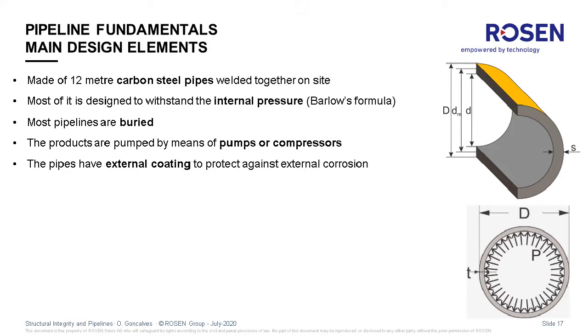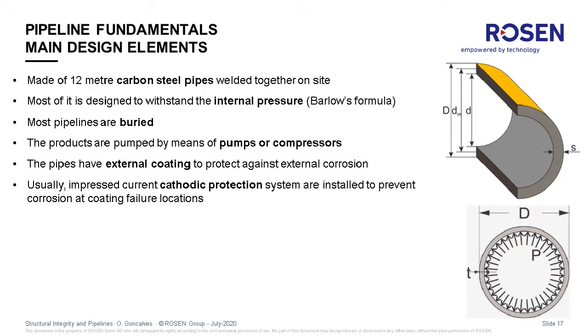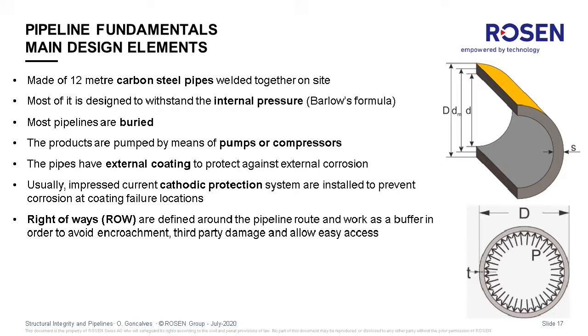Most of the pipelines have an external coating, the objective of which is to protect against external corrosion, which is caused by the soil surrounding the pipeline. And as a second barrier for corrosion, there is cathodic protection, because after some time it is expected that the coating might have some flaws, and in order to protect those areas with flaws, there is the cathodic protection to make sure there is no corrosion, or at least to minimize it, of course.